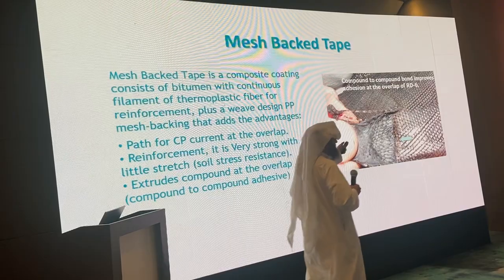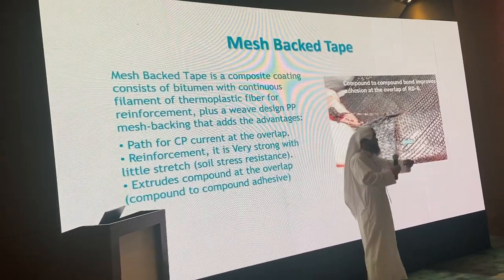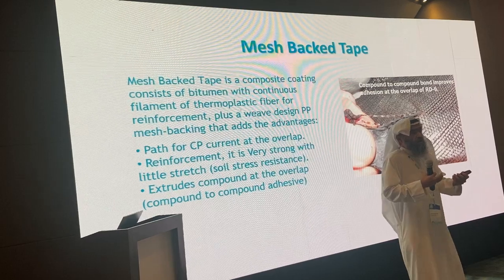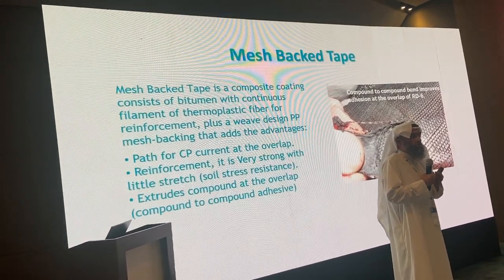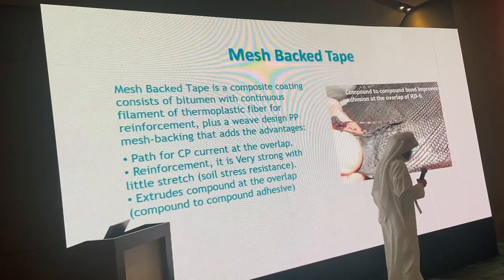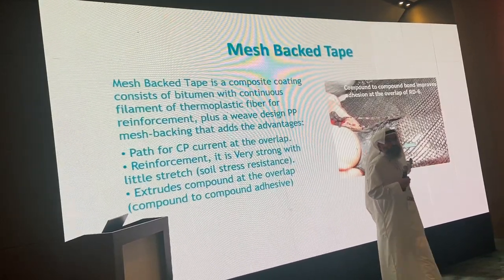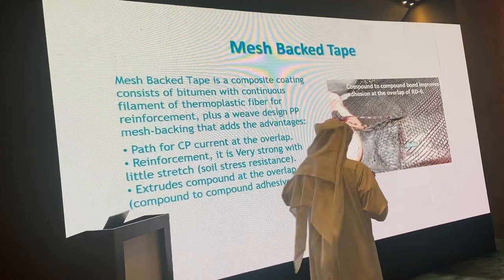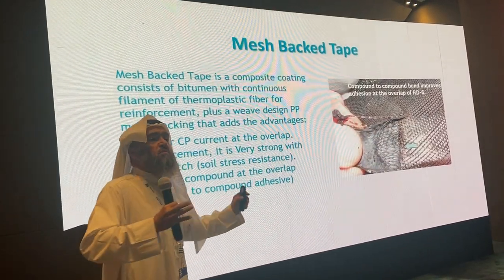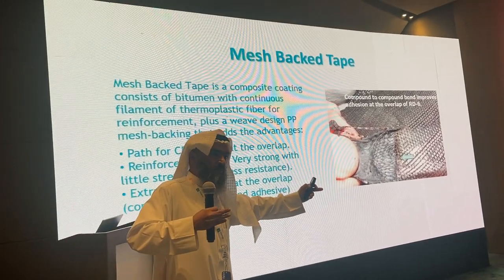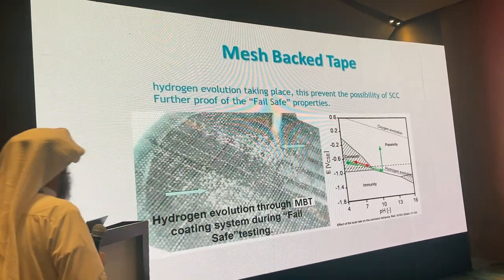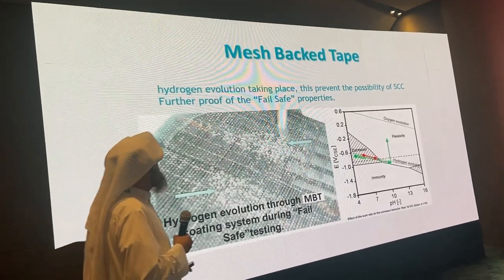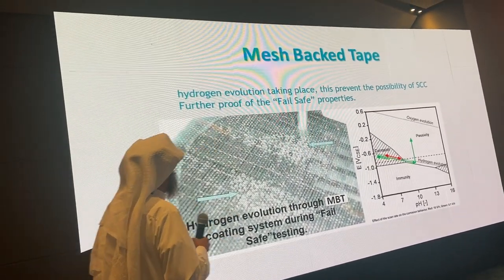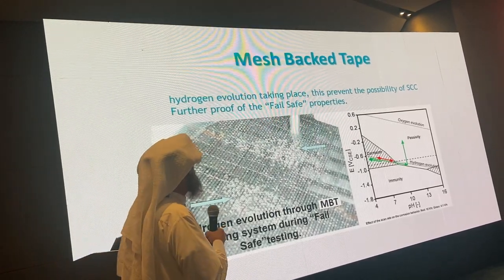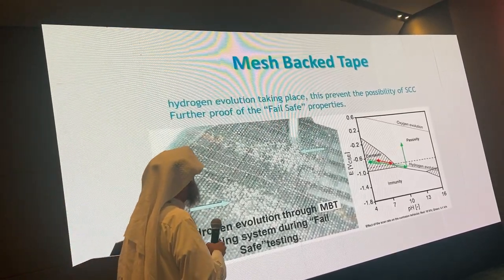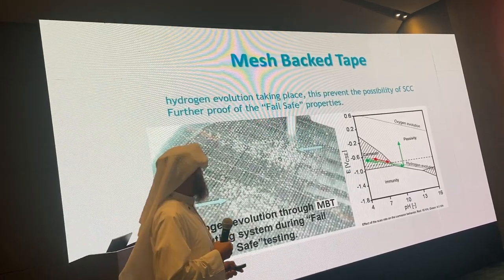Now, to install this type of tape, we use a wrapping machine. That machine assures the tension force that forces the bitumen to come out from the mesh and adhere to its secondary layer. So it is compound-to-compound adhesion. It becomes one piece. It becomes one sleeve. It's not a tape at all. Here you have hydrogen evolution taking place that proves, first of all, stress corrosion prevention, and second, fail-safe property.